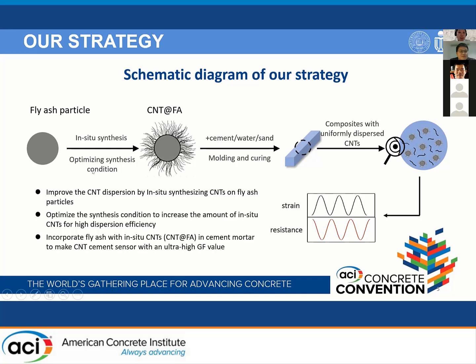In our strategy, firstly, we try to solve the dispersion problem of carbon nanotubes by in-situ synthesizing carbon nanotubes on the surface of fly ash particles. And in this step, we optimize the synthesis conditions to increase the content of carbon nanotubes so as to increase the dispersion efficiency. And then we incorporate these CNT and FA particles in cement mortar. With a good dispersion of fly ash particles, the carbon nanotubes can also be well dispersed in the matrix so that we can get the composites with uniformly dispersed carbon nanotubes. And then we detect the piezoresistivity of these cement composites under compressive loading.